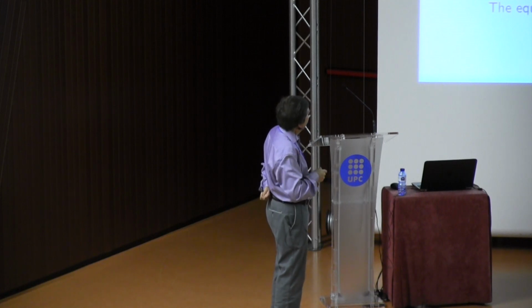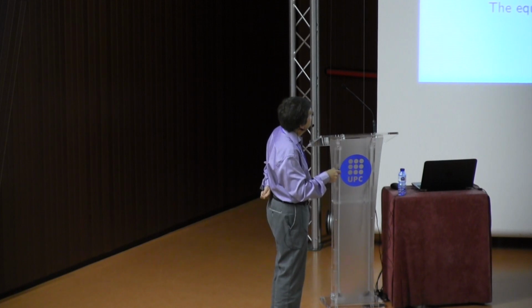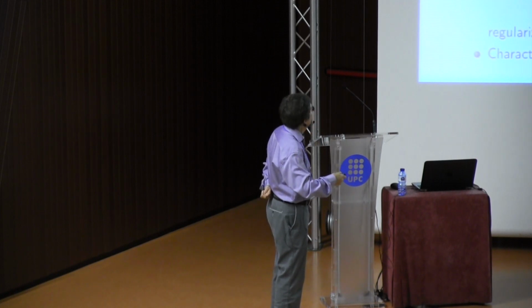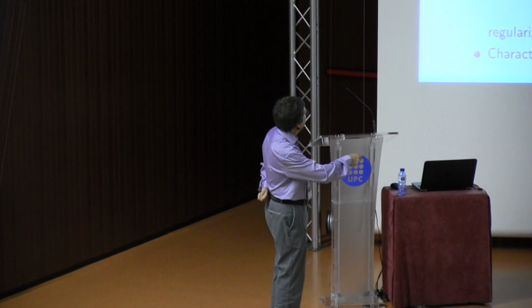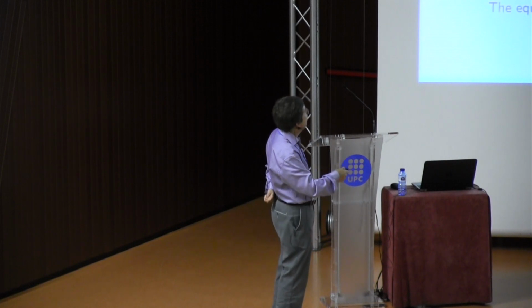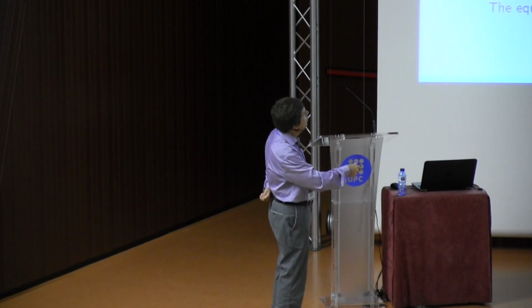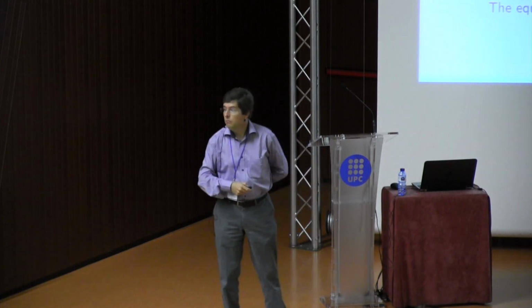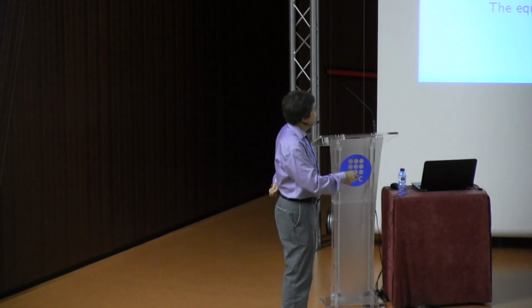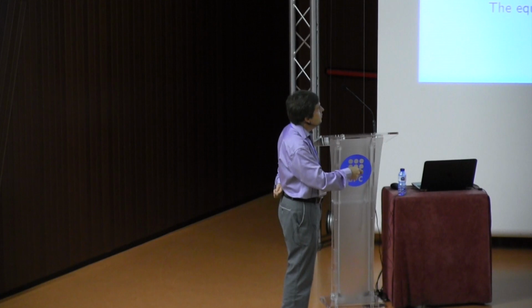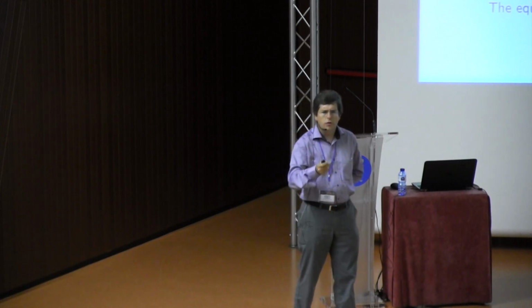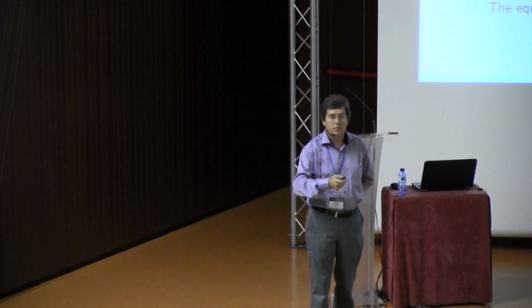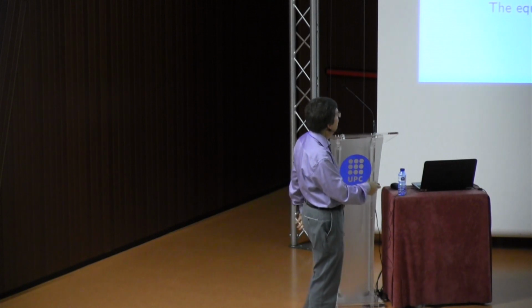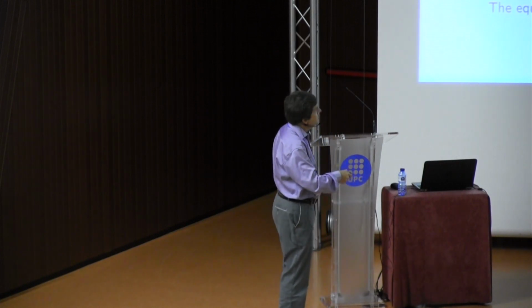And then you assume you have plastic loading, for instance, and you see the difference P minus P chi. You can take it from this balance equation, and you see that now, in your hardening law, you have a Laplace operator. You can compare to the well-known Aifantis model here, where there is a Laplace also, but the Laplace on the plastic strain, in this very old and still useful model.